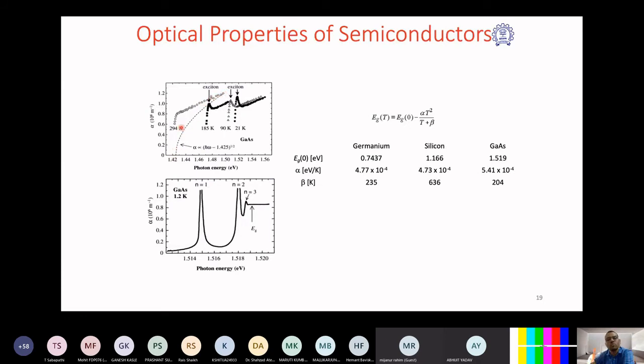If you find that, you will see that with respect to energy, these parabolic relations come into the picture. However, the moment you start reducing the temperature, you go from room temperature to 185 Kelvin, you see your absorption spectrum starts showing an additional peak at the band edge. And this peak becomes much sharper and dominating as the temperature goes down. So that is clear: the exciton cannot dissociate as the temperature goes down, and you find a much more prominent excitonic feature.